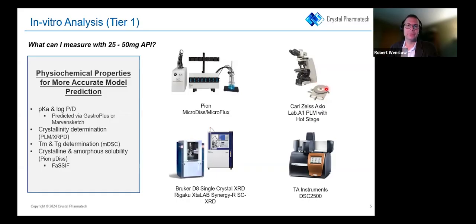You can monitor what happens upon heating. You're going through an actual melting point. What are those bumps on the DSC, what's actually happening there? Well, you can visually get a representation of that with your hot stage microscopy. And again, TGA, DSC, the ability to get melting points, glass transition temperature, giving an indication of if the material is a solvate, a hydrate, or anhydrous.